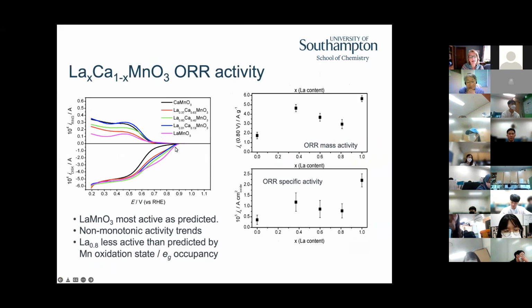Yes. But here, when I have the lanthanum manganate and the ones that are lanthanum rich, what I'm seeing is I am getting reduction current, and this current is rotation rate dependent. So I'm certain I'm not just recording the reduction of the manganese, right? I must be reducing something. I believe it's oxygen, because if I don't purge it with oxygen, I don't see this, right?